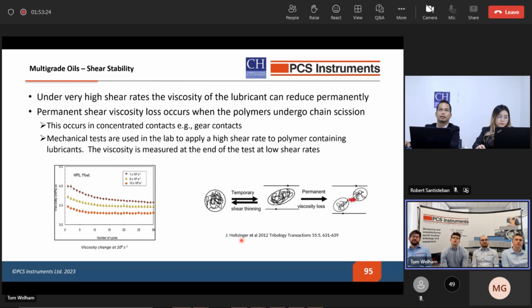Another important effect that can be characterized with a USV is a permanent loss of viscosity. With this effect, long fluid molecules are permanently split by the high shear rate, which results in a drop of viscosity that does not recover. This can be analyzed with the USV. It can be used to run multiple tests on the same sample in series. Here you can see that after a number of cycles, the viscosity drops and then reaches a plateau, simply as a result of intense shearing. So the USV can be used to characterize this effect in lubricants.